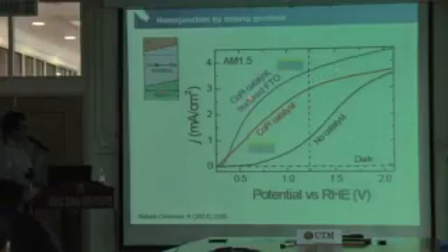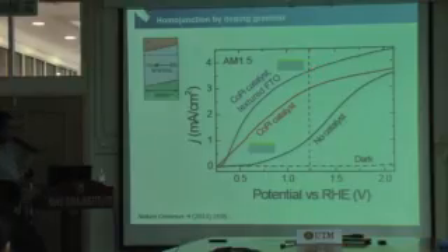So we get a photocurrent of 3 milliamps per square centimeter with this gradient doped bismuth vanadate, and then we improved it further by replacing the FTO or the TCO with a textured TCO, and we get about 3.6 to 4 milliamps per square centimeter with our bismuth vanadate.